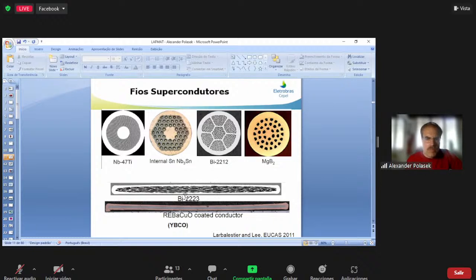However, when you have the BSCCO, the high TC, normally they are highly anisotropic, and in general, you need to use it in this flat tape form. BSCCO-based 2212 can be done, is also anisotropic, but it can be done in round wires. There's a special way to do it. And magnesium diboride is not anisotropic, and it can be done in round wires.